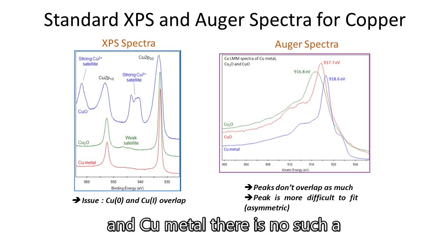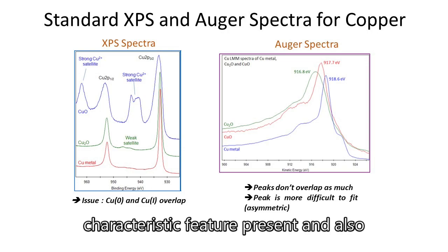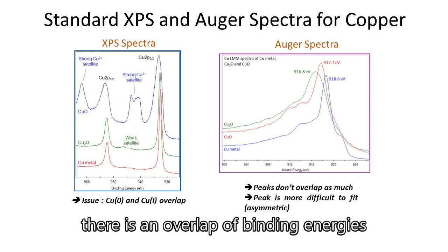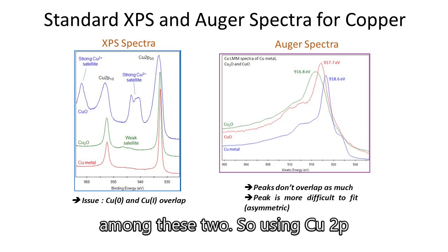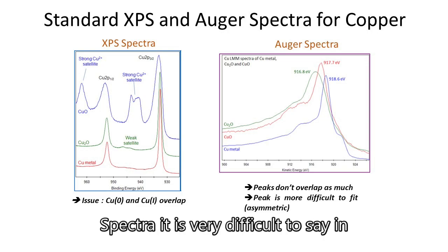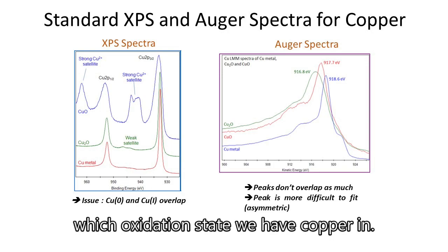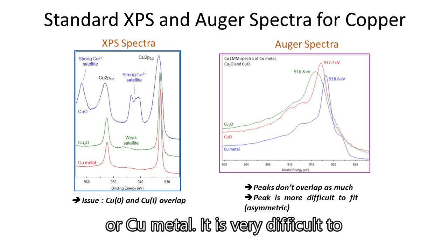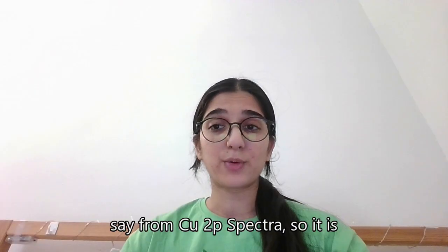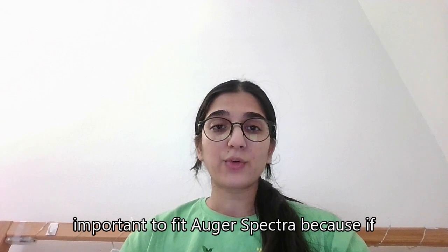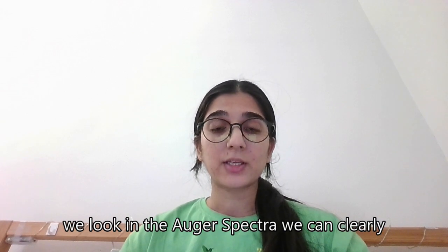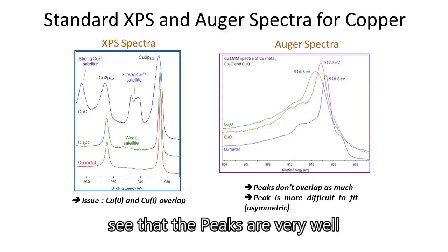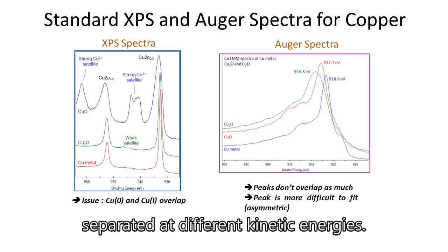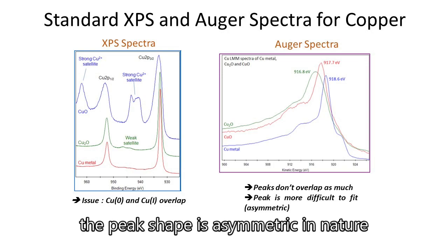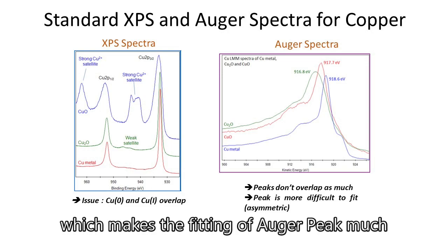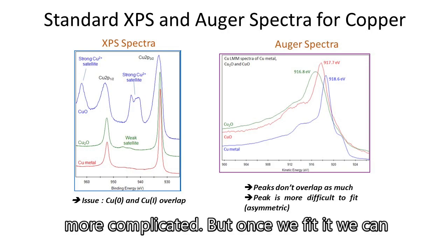But if we look at copper 1 oxide and copper metal, there is no such characteristic feature present, and also there is an overlap of binding energies between these two. So using copper 2p spectra, it is very difficult to say in which oxidation state we have copper. Whether we have copper in copper 1 oxide or copper metal, it is very difficult to say from copper 2p spectra. So it is important to fit Auger spectra, because if we look at the Auger spectra, we can clearly see that the peaks are very well separated at different kinetic energies. But the issue with Auger spectra is that the peak shape is asymmetric in nature, which makes the fitting of the Auger peak much more complicated.